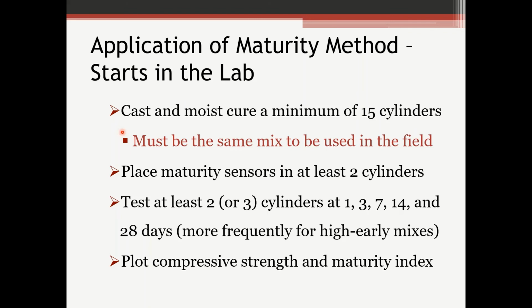You've got to cast cylinders, at least 15 cylinders. It's got to be the same mix that's being used out in the field. So if you're using a 5,000 psi mix out in the field, this is the mix that we make in the lab and make these cylinders. We put maturity sensors in a couple of the cylinders, and then we start to test the cylinders. We're not testing the ones with the maturity sensors in them, obviously. We're testing the other ones, either 2 or 3 if you're making 4x8 cylinders, get the average, and then test them at 1, 3, 7, 14, 28 days, maybe a little bit more frequently for a high early mix. We've done this at 2 and 4 hour intervals over 24 hours, so loads can be applied, roadways can be opened up, things like that, for some high early mixes.